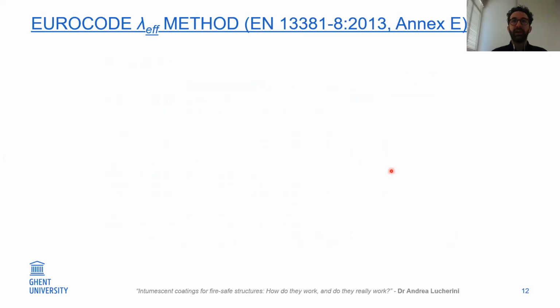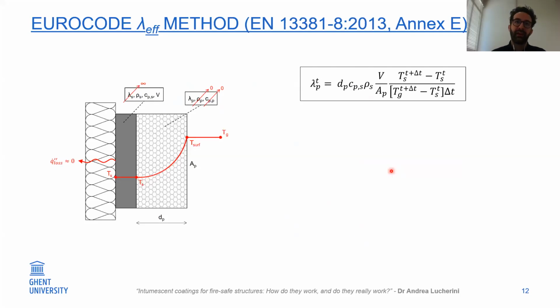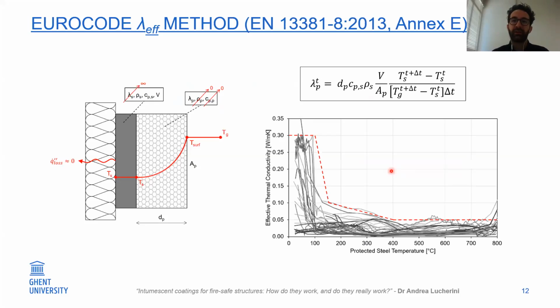Another method, still in the same standard, but in Annex E, is to follow a performance-based design approach where you can calculate the effective thermal conductivity of your coating considering a certain fire resistance test. So what you can get is some certain curves if you plot the effective thermal conductivity, that is mainly the quantification of the insulating properties of your coating when it's exposed to fire, against different temperatures of the steel. And you can do something like that in order to understand the performance of the intumescent coating.